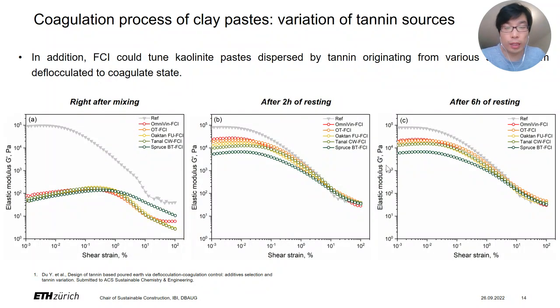So yes, we also tested the citrate with different tannin extracts to make sure it's more robust. Here we chose the tannin extracts from the grape seed and oak trees, but without treatment, and the chestnut trees and the spruce trees. With the citrate one, they all work well. So at the beginning it's quite liquid, but after 2 hours it's kind of rigid. It does not flow anymore.